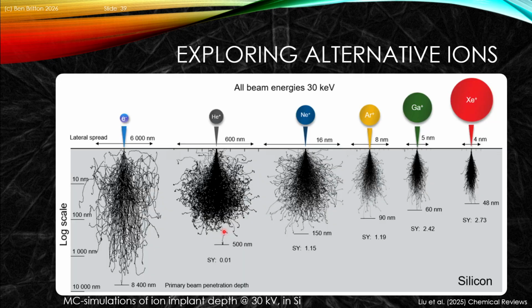There are a range of choices of what you want to do for different sources. We've seen here one example where we've looked at gallium and xenon in some cases, depending on the source sizes, etc. But we can play with different ion types depending on how our electron column or ion column is set up. The interaction volumes will vary, but we can play with the interaction volume sizes, and that can change effectively the probing of our material and what the accessed information is.